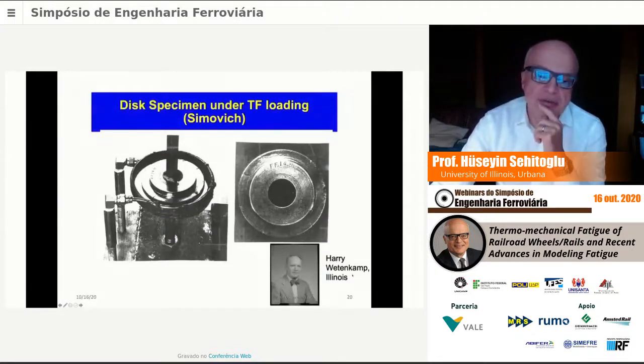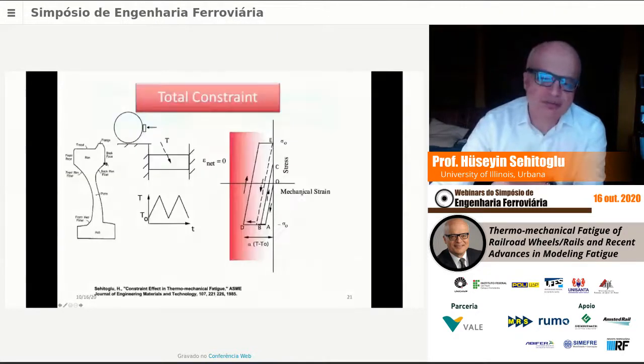Now, if we look at some of the early experiments at University of Illinois, which were done by Professor Wetenkamp and his student Simovich, they took a disk, a small disk, like I would say a 10 centimeter disk. And this is an induction coil, and this is a copper gasket. They cool the gasket, and with the induction heater there's no external force applied. They just heat and cool. This is what we call thermal fatigue loading, TF. And you can see these radial cracks that form after a number of cycles. So this is one of the earliest examples of laboratory thermal fatigue testing.